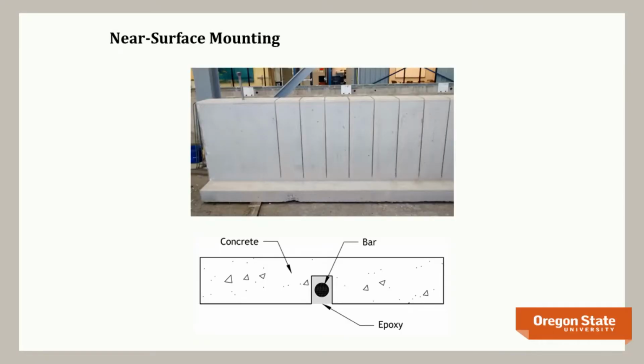So the alternative then for that is what's called near-surface mounting, and that's where you cut grooves in the concrete so you can get a little bit more anchorage in the body of the concrete, but you're still in the cover. And in those grooves, then, you're using a structural epoxy to bond in a type of bar, and carbon fiber is, again, the most common type.